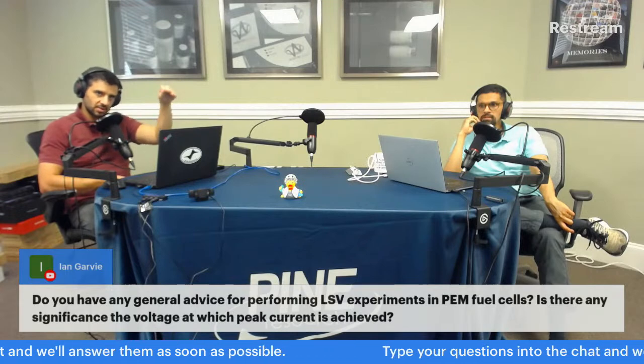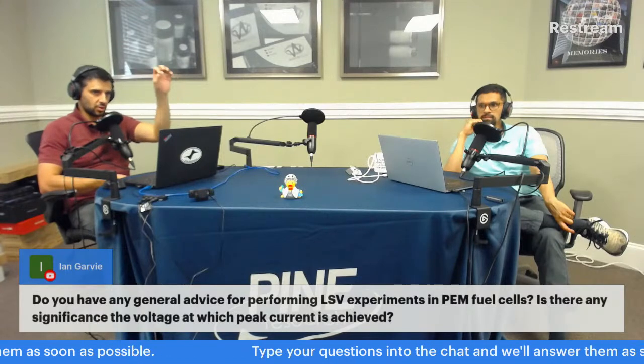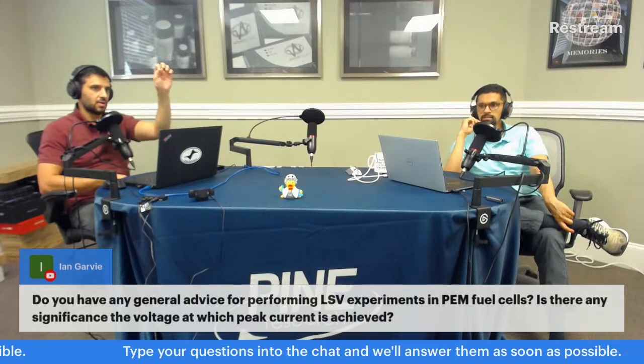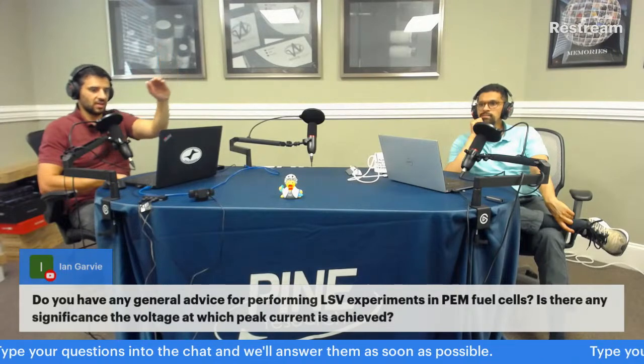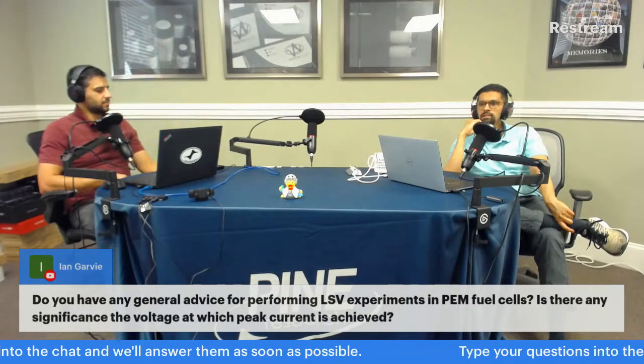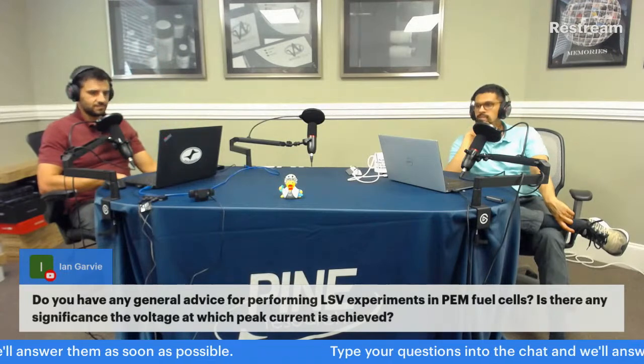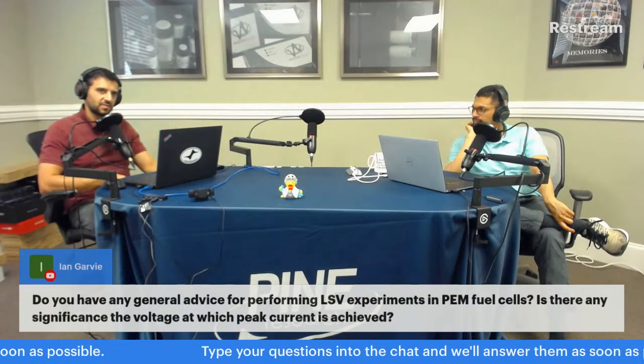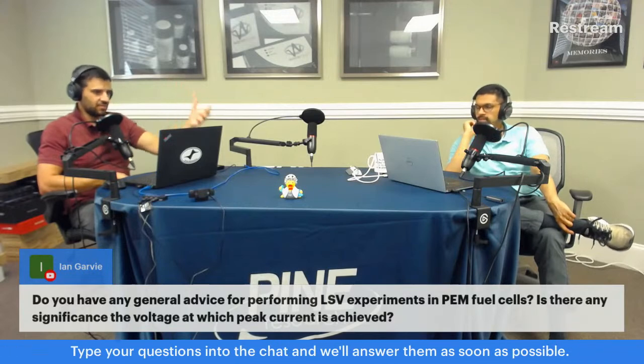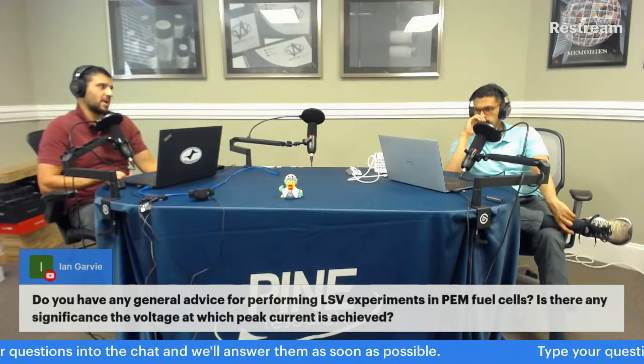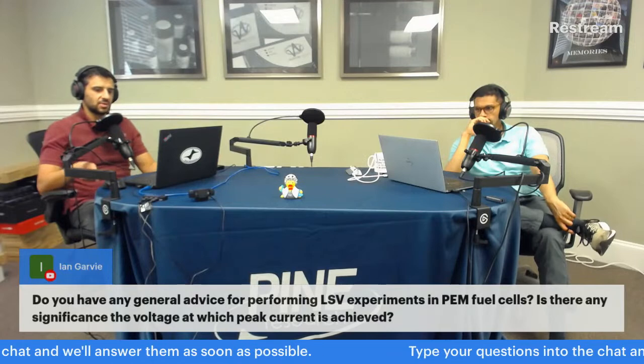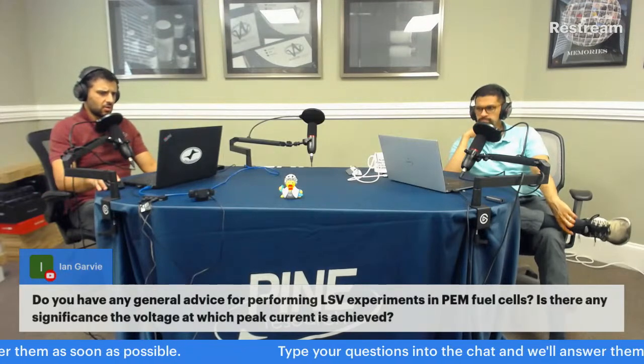But you're just stepping the potential down, seeing what the steady state current is, stepping it down. And then when that's all together, you plot your steady state current versus the potential, and you get a pseudo LSV curve. You're taking some diffusional, capacitive effects out because you're not scanning really fast. When you scan faster, you have more capacitive effects. And so you take some of those out.